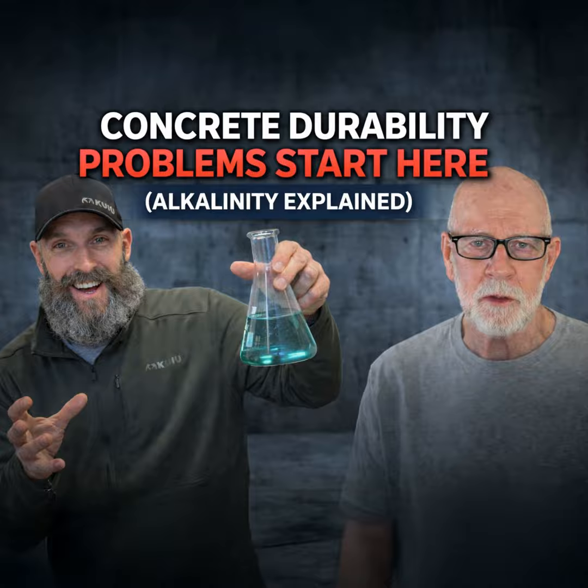Well, people say, well, that's no big deal. Yeah, it is a big deal, because at 80% and under, cement formation stops. That water is no longer available to the cement. If it's not available to the cement, you get a more porous, permeable surface. And that's what we keep doing. So even if you put water on top, it will not allow the water to penetrate. Right. Because it's now in an equilibrium.